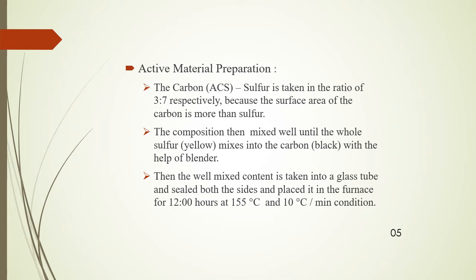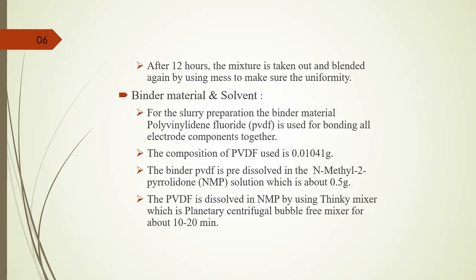using a blender until the sulfur, which is yellow particles, was well mixed into the carbon particles, and then I used a furnace for 12 hours at 155 degrees Celsius, with the temperature rising at 10 degrees Celsius per minute. In this condition I kept the active material, which I had blended homogeneously in the ratio of 3:7, in the furnace for 12 hours. After that, the above mentioned binder material and solvent.